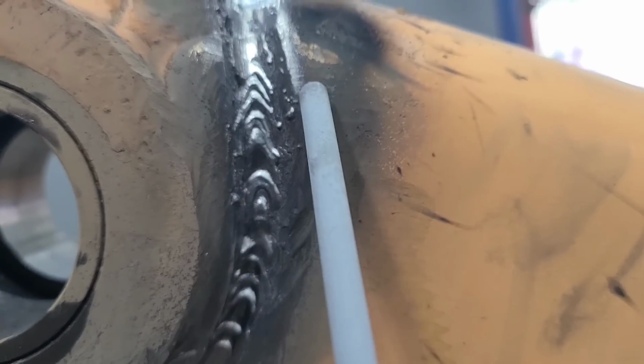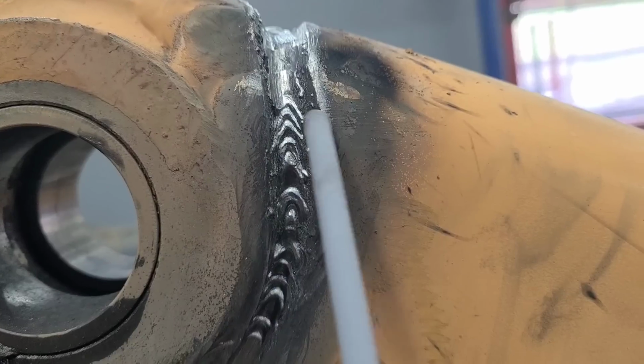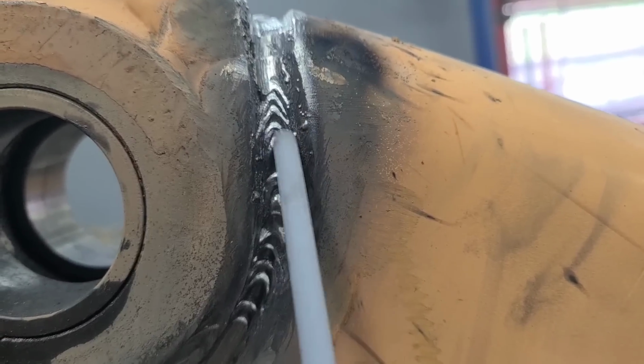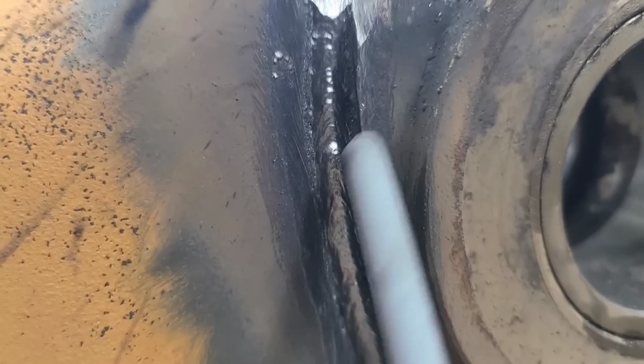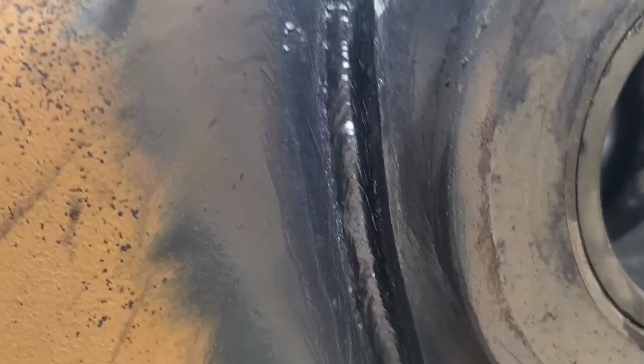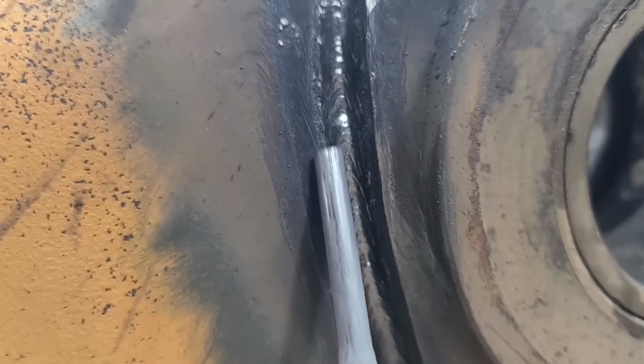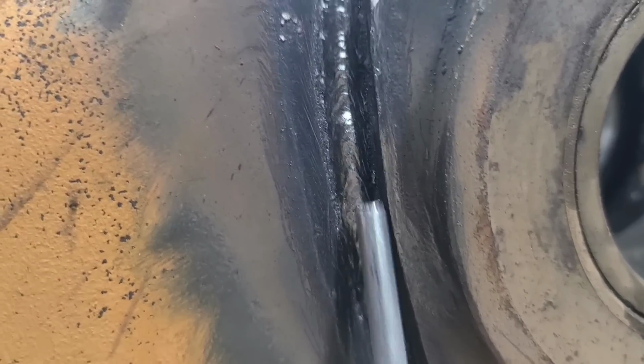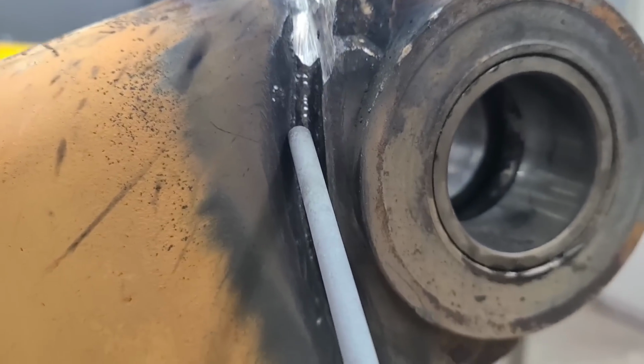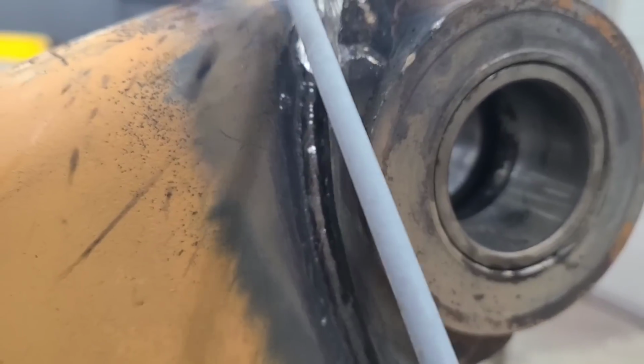You see, this weld over here is more of a concave weld, a cup-shaped weld. This is ready to weld on. This root bead over here, if you look at each side of that, you'll see there's spots here, real deep areas. These are wagon tracks, and there's slag stuck in there. And that's a situation created by that root bead that had to be put in there to fill this up.